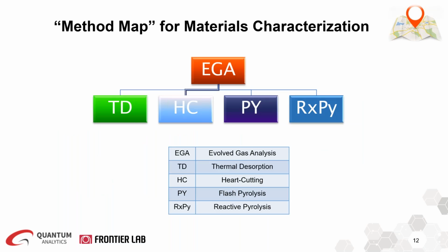We have created a series of techniques referred to as the method map to chemically characterize samples using the multi-mode pyrolyzer. EGA, which is evolved gas analysis, is the first step, which provides a clear picture about the thermal profile of the sample as well as the optimal temperature zones for the next step. So EGA really guides you what to do next. It will show if a thermal desorption, heart cutting, or flash pyrolysis is needed, or if a combination of the techniques is required.